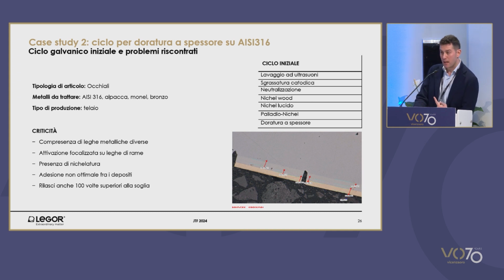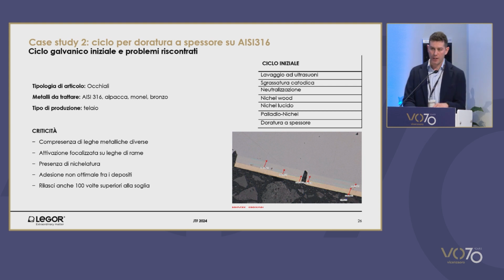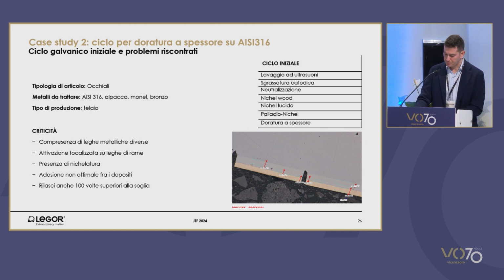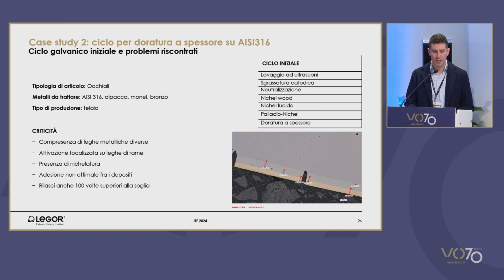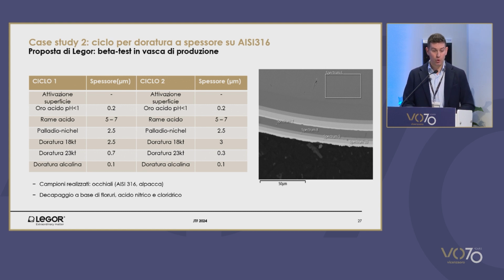Another critical issue that you can see quite easily with this electron microscopy image showed that these thick electrodeposition layers could cause problems, because adhesion between the different layers might be failing, or there could be cracks that might not be visible. Such cracks can lead to the migration of nickel from the object to the wearer. The nickel included in the stainless steel alloy, and the releases in this case were unacceptable.